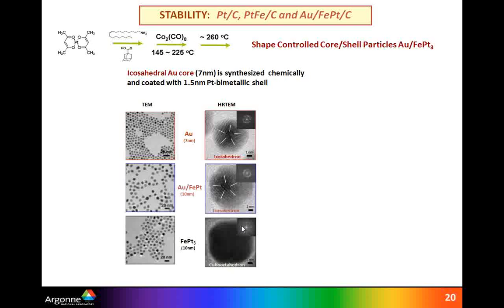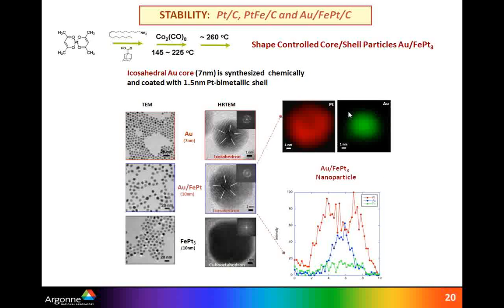And also we wanted to compare how all of that is going to match activity and durability of comparable pure platinum iron particles, which is given here. So the same particle size and the same loading. We did a number of characterizations, including high-resolution TEM and also elemental mapping, and it was confirmed that gold stayed inside while platinum shell with iron was around the particle.